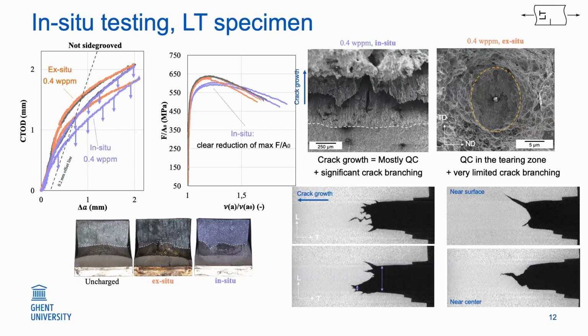This kind of phenomenon is also a bit happening in the ex situ tests because we have no side grooves in these in situ tested specimens, so we also need ex situ without side grooves to have a fair comparison. And we can see at the edge, because of the stress state there, we do have a tiny bit of a branching crack, but in the center, it is a single crack. So there's no real branching in the ex situ tests. Yeah, so this means we are likely overestimating our CTOD just by our double clip gauge method.